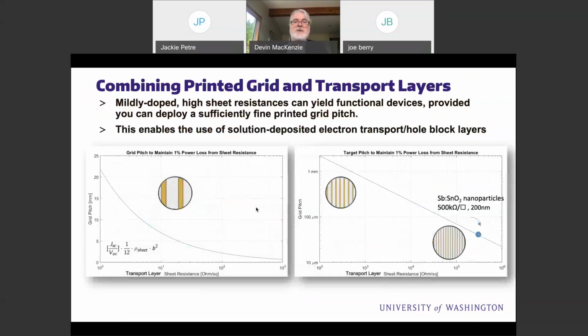So we looked at what we do well in the rest of our work in our lab, which is ultra high resolution printing. And so we did some modeling and simulation to show that combinations of a printed grid plus a relatively mildly doped, high sheet resistance transport layer can actually achieve very attractive figures of merit. So this is the example, 1% power loss from sheet resistance. Remember, we're talking about 10 to 15% for ITO, so this is much lower than the power loss from the sheet resistance of ITO. And these are all scaled to 90% transmission.